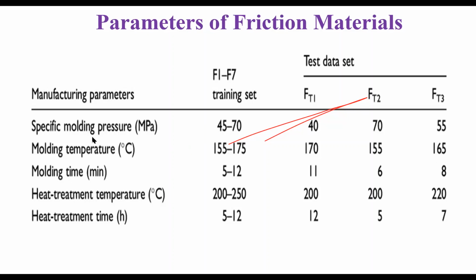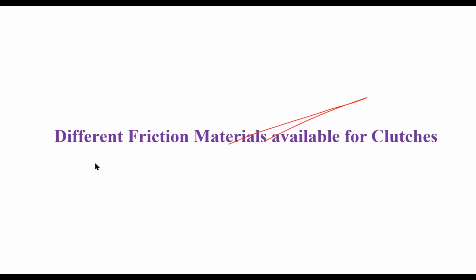Say, for example, the specific molding pressure between 45 to 70 MPa is what is being used for the friction materials, and the molding temperature ranges between 155 to 175 degrees Celsius, the molding time between 5 to 12 minutes, and the heat treatment temperature of 200 to 250 degrees Celsius, and the heat treatment time is 5 to 12 hours. So when you're designing the friction material for the clutches, you need to consider all these manufacturing parameters, and select according to these parameters to design the friction material for manufacturing that particular friction material into the clutch.